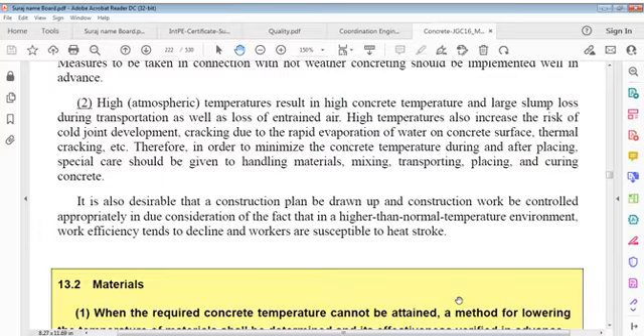High atmospheric temperature results in high concrete temperature and large slump loss during transportation, as well as loss of entrained air. High temperatures also increase risk of cold joint development, cracking due to rapid evaporation of water on concrete surface, and thermal cracking.